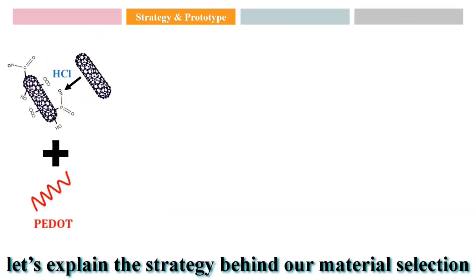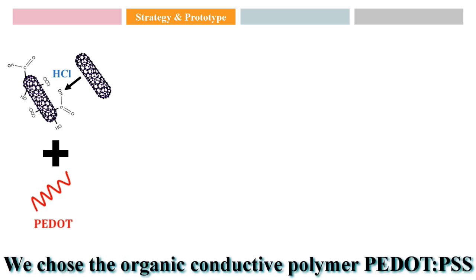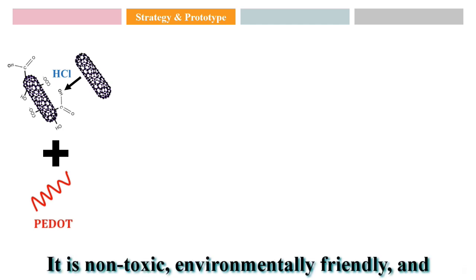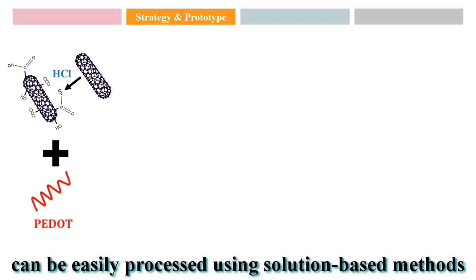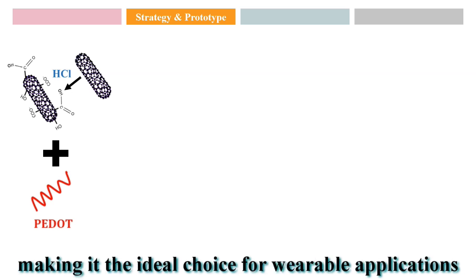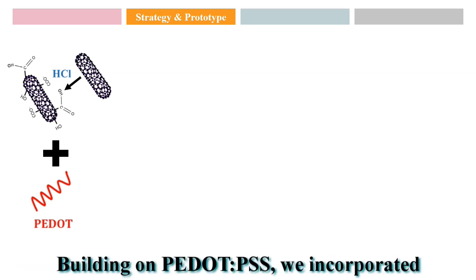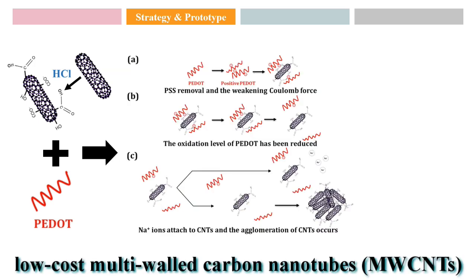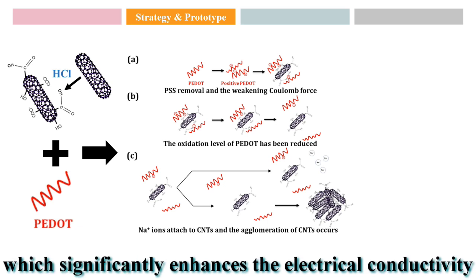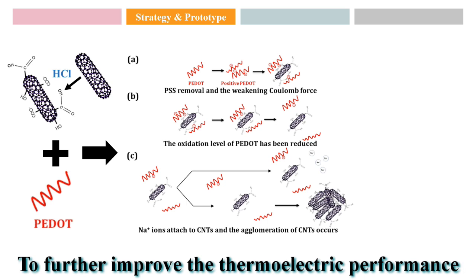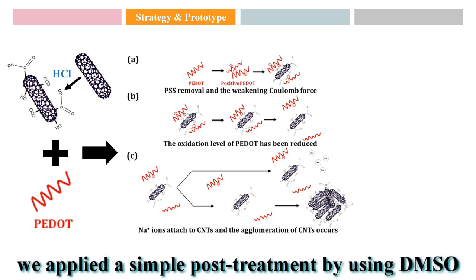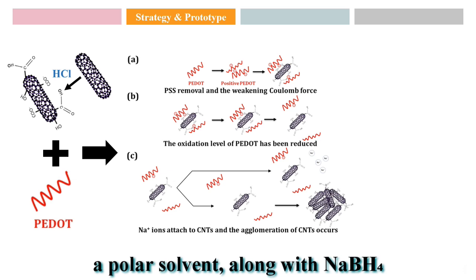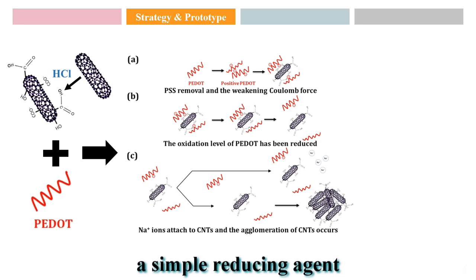Now, let's explain the strategy behind our material selection. We chose the organic conductive polymer PEDOT:PSS as our base material. It is non-toxic, environmentally friendly, and can be easily processed using solution-based methods, making it the ideal choice for wearable applications. Building on PEDOT:PSS, we incorporated low-cost multi-walled carbon nanotubes to form a composite material, which significantly enhances the electrical conductivity. To further improve the thermoelectric performance, we applied a simple post-treatment by using DMSO, a polar solvent, along with sodium borohydride, a simple reducing agent.